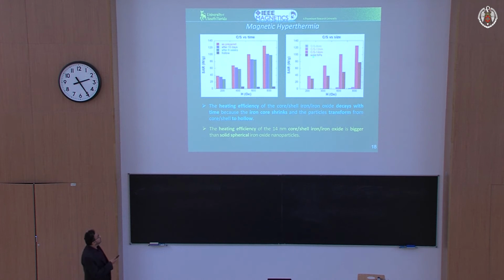Okay? So yes, the proof of concept worked. We thought that the SAR should go up, it did, as it should, right? So comparatively, if you take the solid nanoparticles and the core shell particles, it's at a higher SAR as soon as you synthesize it. Our happiness, unfortunately, was short-lived, precisely a few days to a few weeks at most. And here is a chart that shows the SAR, and you can see that as a function of time, the SAR value drops, and eventually when the particles become hollow, they are useless.